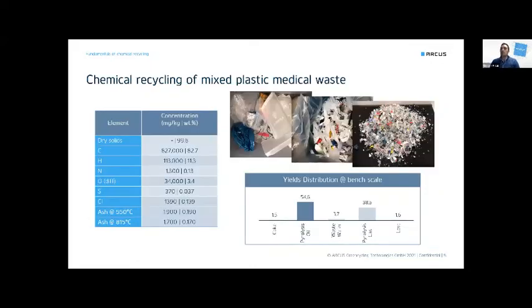So moving forward, what do we have with the pyrolysis process? Have a look at one feedstock. You see there, what we always do is an elemental analysis, looking specifically at contaminants, so nitrogen, oxygen, sulfur, chlorine, but also inerts like ash. And you see that's the case for a medical plastic waste where contaminants are relatively low, but still too high for new medical application.